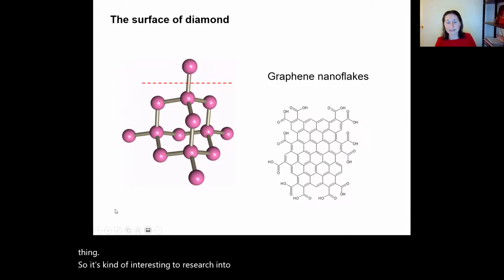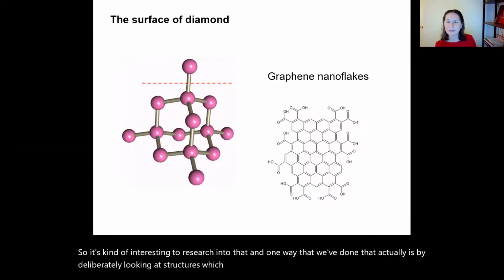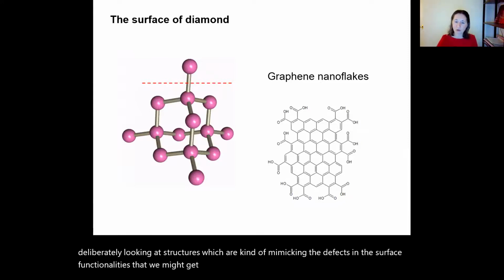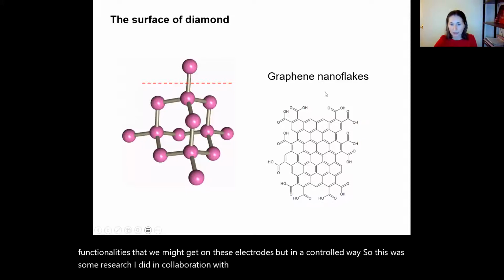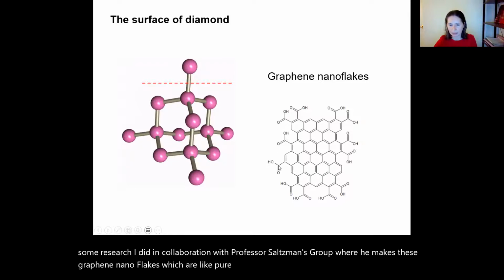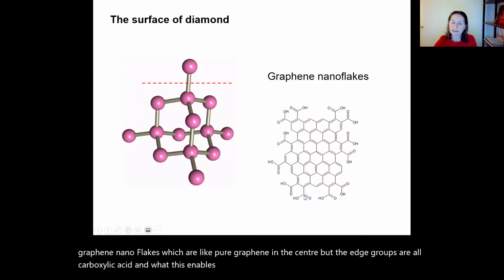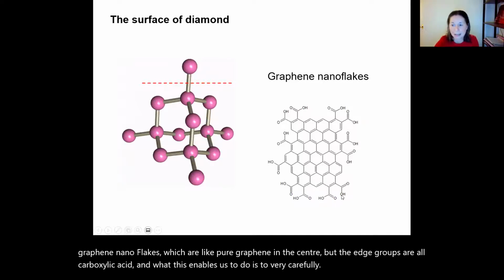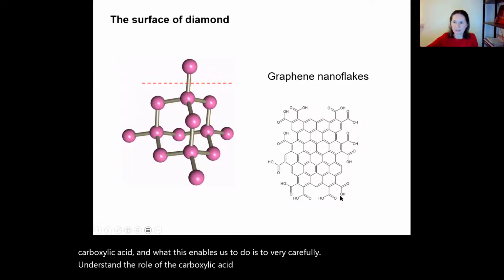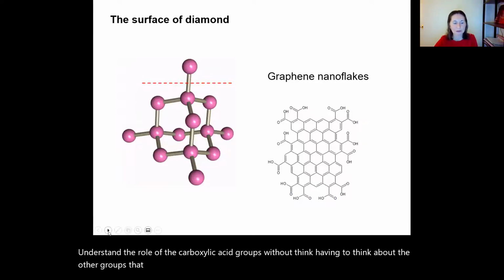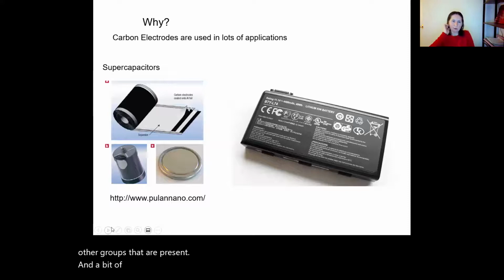And one way that we've done that is by deliberately looking at structures which mimic the defects in the surface functionalities that we might get on these electrodes, but in a controlled way. This was some research I did in collaboration with Professor Saltzman's group, where he makes these graphene nanoflakes, which are like pure graphene in the center, but the edge groups are all carboxylic acid. What this enables us to do is to very carefully understand the role of the carboxylic acid groups without having to think about the other groups that are present. And a bit of context of why we might want to do this.